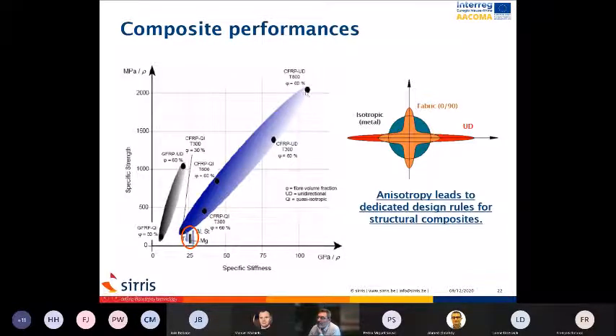I will now go a little bit more into detail on what CFRP UD T800 with a Phi factor of 60% is. That means carbon fiber reinforced plastic, UD reinforcement, you know what UD is. T800 means that you use a very high performance grade of carbon fiber, and the Phi factor is the fiber volume fraction in the composite. That means that you use a process that is able to put 60% of fiber into the full volume of the product. This is a high capability technology or process. And with this, you can have a very, very high improvement compared to the conventional metal.